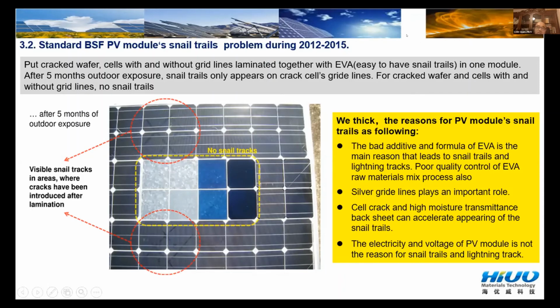So from all these phenomena and the research report, we can get the conclusion. We think the reason for PV module snail trails is as follows. The first is that bad additives and formula of EVA are the main reason that leads to the snail trails and the lightning tracks. Poor quality control of EVA raw material, or maybe some additives, the quality is not so good. Maybe they do not mix the process very well. So that will cause the problem.